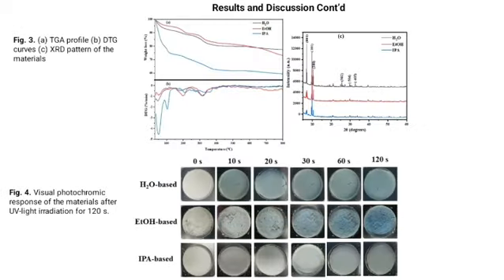The thermal properties of the heterostructures reveal three substantial stages of weight loss, which could be due to the decomposition of different components in the material. The weight loss at less than 100 degrees Celsius is due to the loss of absorbed water molecules at the first stage, while the second stage of weight loss at temperature greater than 100 to about 243 degrees Celsius could be the decomposition of the labile oxygen-containing functional groups and intermolecular bonds. In the third stage of weight loss at temperature greater than 384 degrees, a residual mass of 81%, 97%, and 62% were found in the water, ethanol, and isopropyl alcohol-based materials, respectively, and these weight losses could be due to the denaturation of the materials.